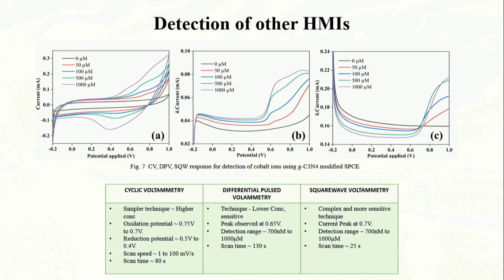We also found that it can detect cobalt ions at lower concentrations, around 1 micromolar to 1000 micromolar. So we use this technique: if it's a higher concentration, we can go for cyclic voltammetry, if it's a lower concentration we can go for DPV, and if you want an instant result we can go for square wave voltammetry. And that's all.